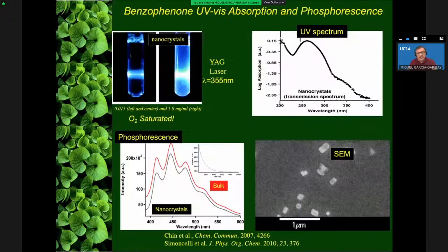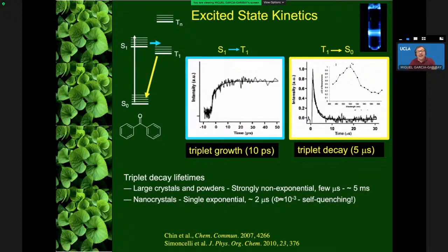Here we see how by using nanocrystals, we can detect the phosphorescence in the bottom left. We can compare the phosphorescence of the nanocrystals with the phosphorescence in the bulk. On the top right, we can see that we can collect the UV spectrum by doing transmission spectroscopy. And if we do scanning electron microscopy, you can see that these crystals are about 200 nanometers, which is, again, smaller than the wavelength of light that we're using, that in this case is 355 nanometers. Because of that, we can do transmission spectroscopy.